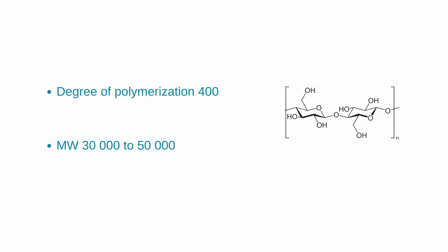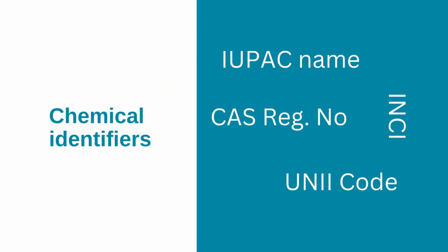Finally, native cellulose has a degree of polymerization of 10,000, corresponding to a molecular weight of 2 million. During production, the hydrolysis process fractures the polymer chains, which reduces the degree of polymerization to less than 400, giving MCC a molecular weight of between 30,000 and 50,000.